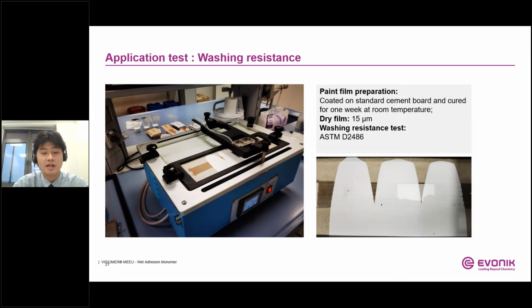So in order to test the effect of MEU on improvement of adhesion in construction paints, this is a wash-resistance test done according to the external wall coating scrub-resistance method, ASTM D2486. After 1 day, paints were coated on the standard cement board and cured for 1 week at room temperature, and the dry film thickness controlled at 15 micrometers.